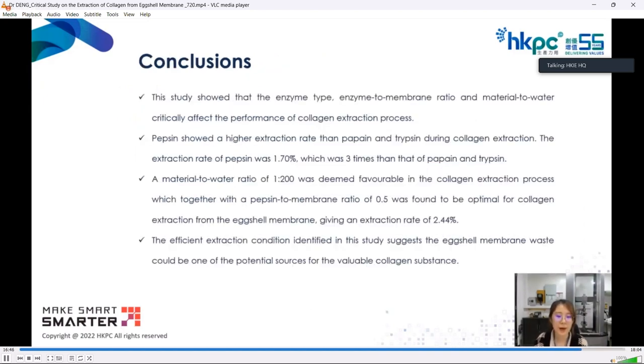Here is the conclusion part. This study showed that there are three critical parameters that can affect the performance of the collagen extraction process. Pepsin showed a higher extraction rate than trypsin during the collagen extraction. A material to water ratio of 1 to 200 was favorable in the collagen extraction process, together with the pepsin to membrane ratio of 0.5.